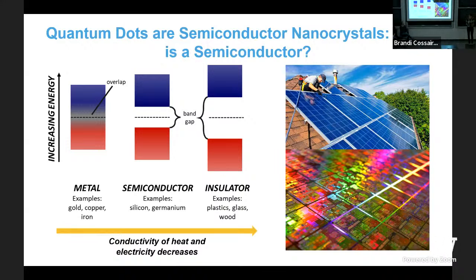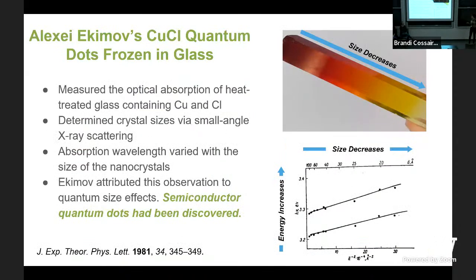Semiconductors are important in our everyday lives for everything from solar panels to the chips inside of our phones. And so, like Brandi mentioned earlier, Alexei Ekimov is credited with the first quantum dot synthesis. He made copper chloride quantum dots frozen in glass. And scientifically, what he found was interesting about these was that the absorption was dependent on the size of the nanoparticles. He found that the larger nanoparticles had a redshifted absorption relative to the smaller nanoparticles. In a later paper with Alexander Efros, Ekimov would go on to attribute this phenomenon to quantum confinement.